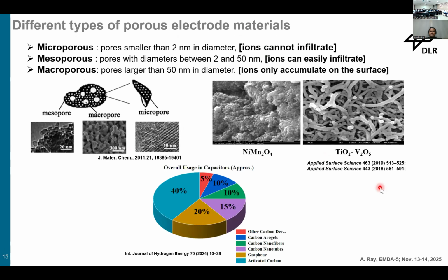For charge storage, porous material is very superior for supercapacitors. There are micropores, which are in the range of less than 2 nanometers in diameter, so ions cannot infiltrate. Mesopores have pore diameters between 2 and 50 nanometers, which means ions can easily infiltrate through these pore structures. And macropores are larger than 50 nanometers in diameter, which means ions only accumulate on the surface. They cannot infiltrate through these pores.